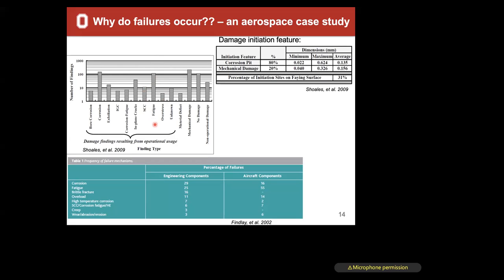And when they looked at any damage that was cracking related, so fatigue, stress corrosion cracking, corrosion fatigue, any kind of crack that was emanating from that damage, they went back and said, what's that damage initiating feature? What's the thing that caused that crack to start? 80% of the time it was a corrosion pit, right? So if a corrosion pit started it, the environment didn't go away. So a lot of these fatigue failures, what they call just fatigue, technically would be classified into environment-assisted cracking and corrosion fatigue because of the fact that a corrosion pit started it.